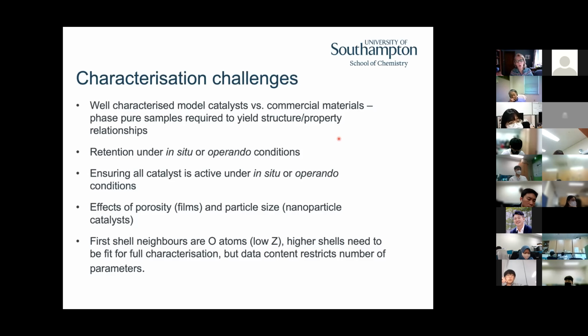If you've got a very wide particle distribution, when you have a per atom average, the big particles actually get weighted more in your XAS analysis than the very small particles. So you need to be careful. Also, in terms of commercial materials, you may have different composition ranges. And so you really need to think about what you're looking at.